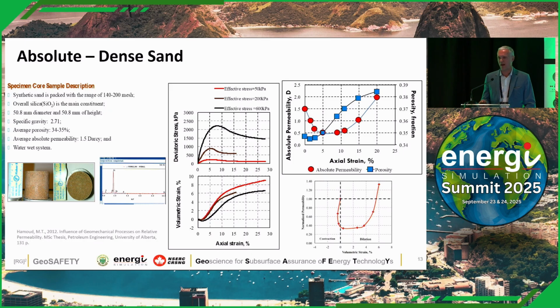And one of the things we found is the kind of thing I think most people would be familiar with, right? I do triaxial compression. This is back then, a triaxial compression test. That's the stress-strain curves. There's the volumetric strain. And when I look at the data you looked at before, the blue is porosity. So remember, with the volumetric strain, the porosity goes up, but the permeability for the first part of this whole test actually drops like crazy. So I'm using a triaxial compression path, but my permeability is just reducing like crazy.